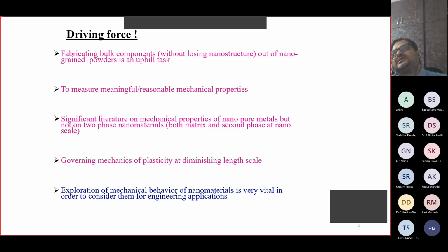And when you have planes missing, see, all these crystalline materials will have a stacking sequence. Like if it is FCC, you will have an ABC kind of stacking. A is one plane, B is another plane, C is a different plane. Likewise, hexagonal close-packed materials will have a stacking sequence like AB, and so on. A is one plane, B is a different plane compared to A. So when you have a regular sequence like this, you have no issues. But the moment you bring an additional plane into this sequence, or if you remove an existing plane from the original sequence, then you create defects called stacking faults. And these stacking faults also would help you in making mechanical response viable.